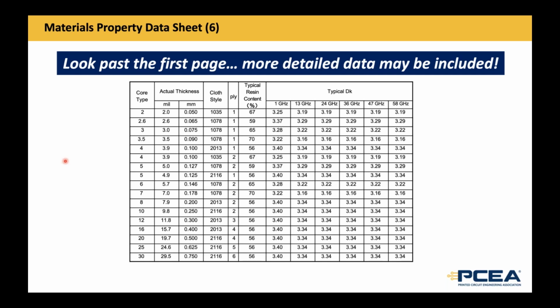One of the Easter eggs in our data sets that is not always published on the web, but is often part of the package that we hand out at a trade show or is online as additional data, is that we've measured and verified at different frequencies for both Dk and Df for a lot of our products, because it helps you to understand. If you look at the resin content column, typical resin content, you can see that there are from 56 up to 70% represented in these constructions that are all for different thickness laminates. And you can see that for Dk, there's certainly an important difference between them, and it's different for frequencies.